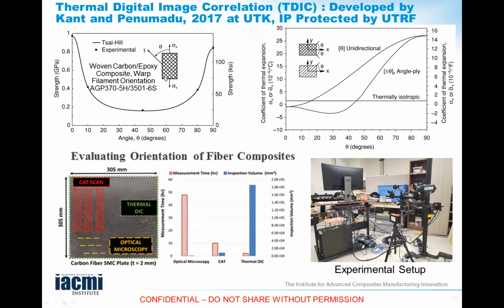So if you look at a continuous composite and do mechanical property testing, the strength is extremely dependent on the fiber orientation. And the same thing, obviously, we have seen for the platelets and discontinuous SMC-based systems. But one very important attribute we can gain from carbon fiber composites is that the thermal expansion coefficient of carbon fiber along the fiber direction is negative. So when you heat it, they actually contract, and along the matrix direction is fairly large.